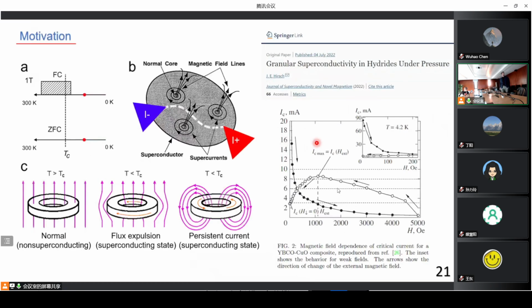A bit later, maybe several months later, or maybe several months before, Jorge Hirsch published a paper that a similar effect should actually be observed in voltage-current characteristics and in critical currents. He gave one example when the authors investigated YBCO and found that critical currents depend on the history of the sample. There is an obvious hysteresis loop, which depends on the history of the sample, on the question of whether this compound was before in the magnetic field or not. So again, this picture explains my logic and my idea.